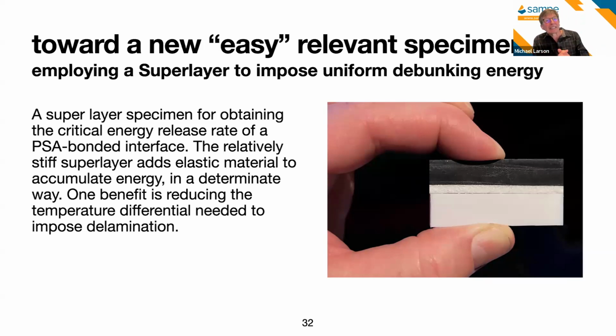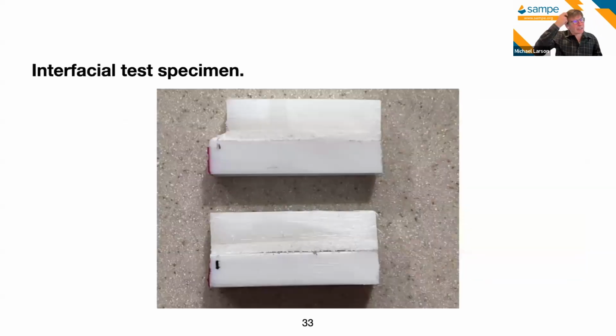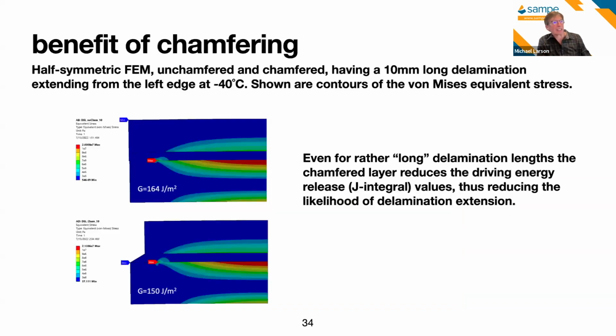So the super layer is, in this case, we've bonded the lower two white colored layers, and we're slapping a much stiffer material on the top in order to be the driving source for the delamination to occur. And we tried a number of different specimens with and without a chamfer. So here are two specimens that we prepared with a similar and just a Sharpie marked delamination that we put in ahead of time, where the PSA is not bonded between that lower white level layer and then this middle layer. These specimens we used, the super layer is the same stiffness as the substrate material, thinking about that as a way of simplifying the analysis.